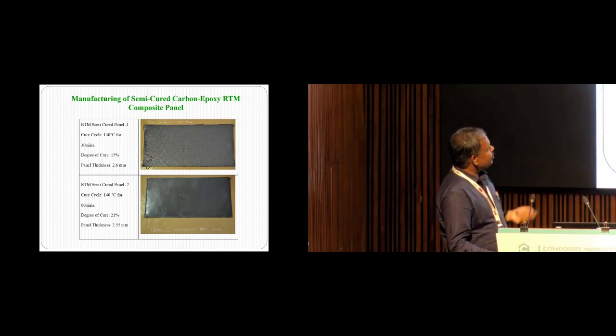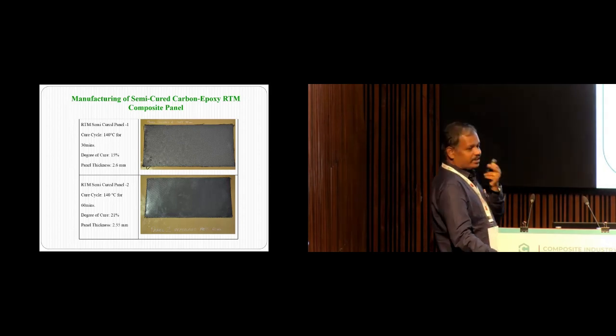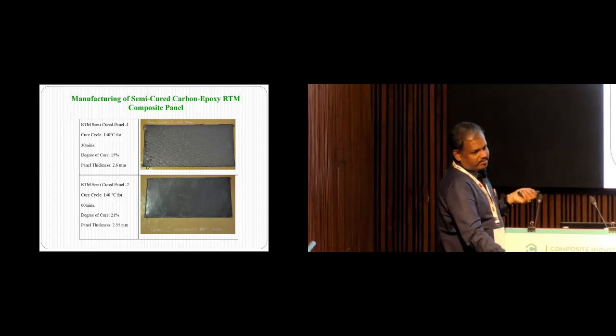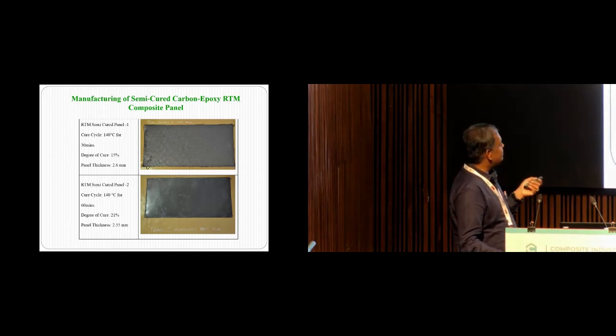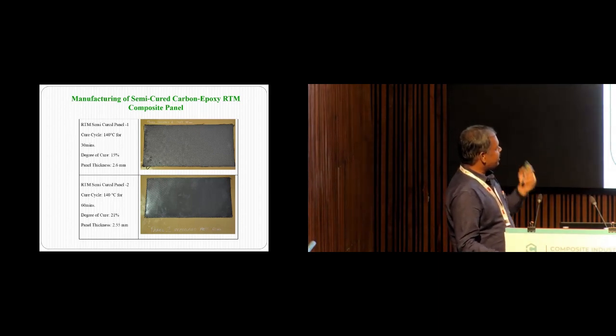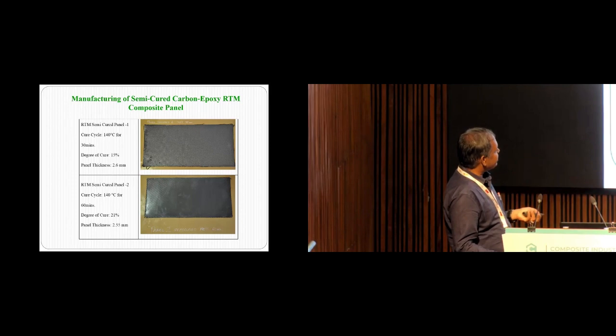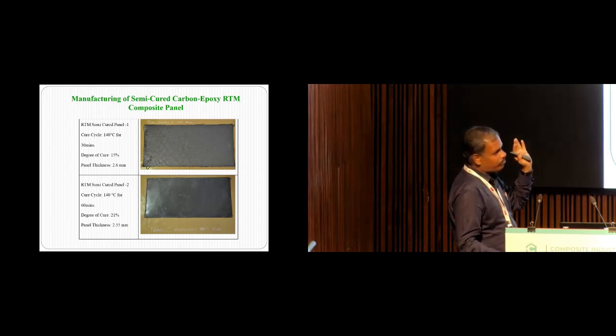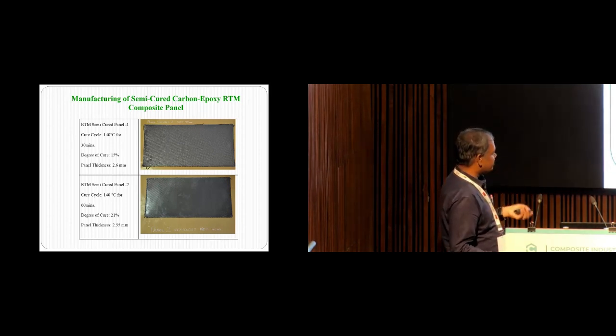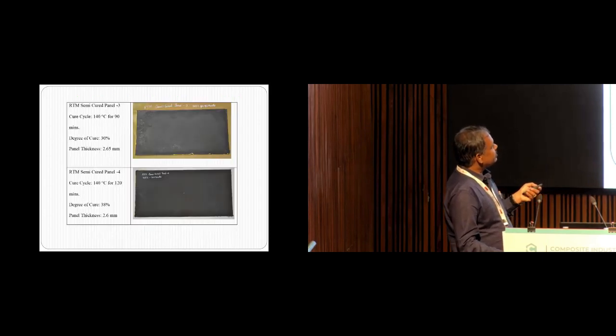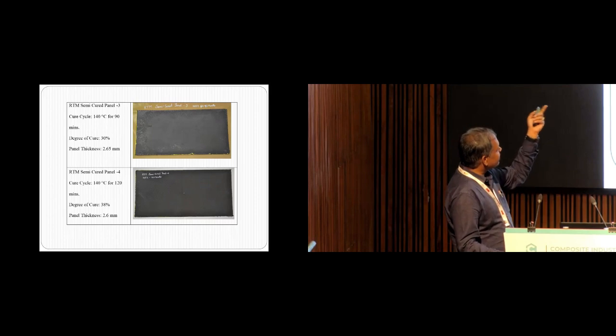First we took a cure cycle of 140 degrees centigrade for 30 minutes. We got a degree of cure of 15% and a panel thickness of 2.6 millimeter. The second one is 140 degrees for 60 minutes, which got us 21%. So 140 degrees for 30 minutes got you 15%, and 140 degrees for 60 minutes got you 21%. Again, for different time factors, 90 minutes and 120 minutes, the calculation here is 30% and 38% respectively.